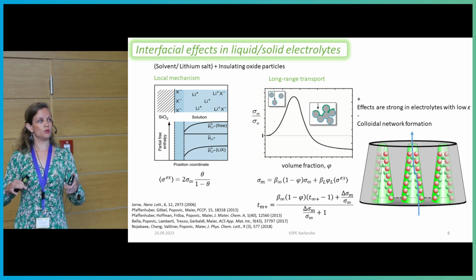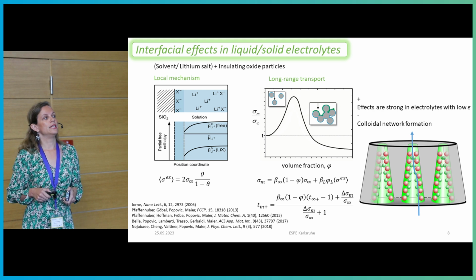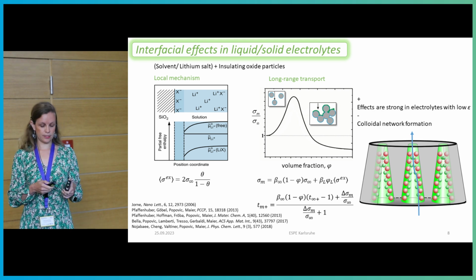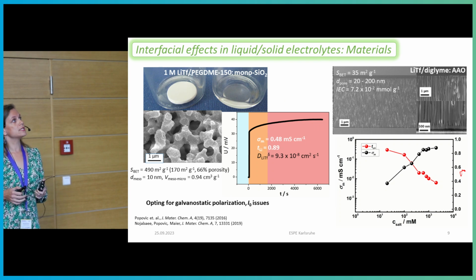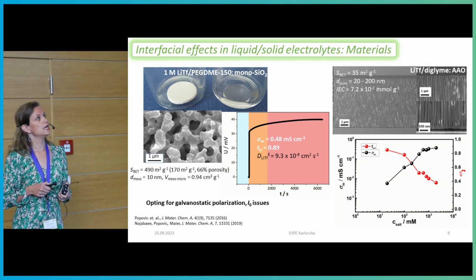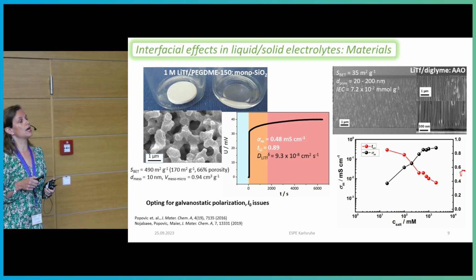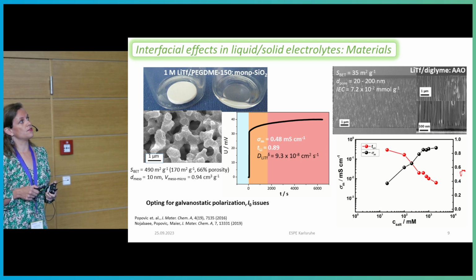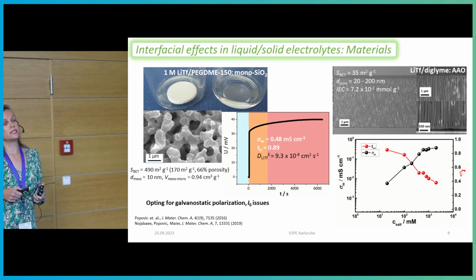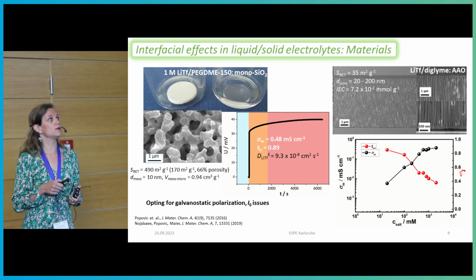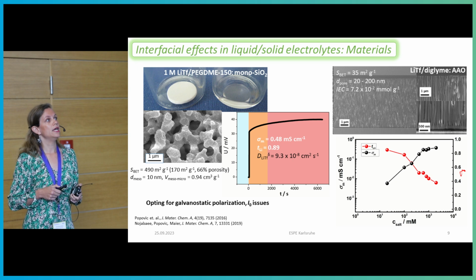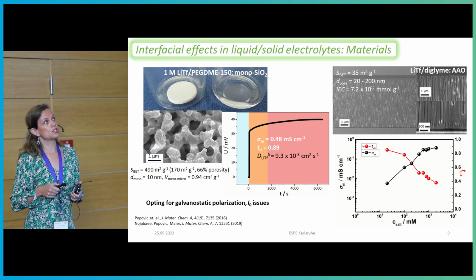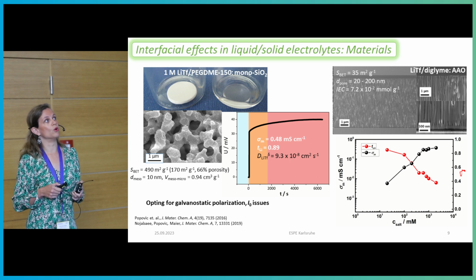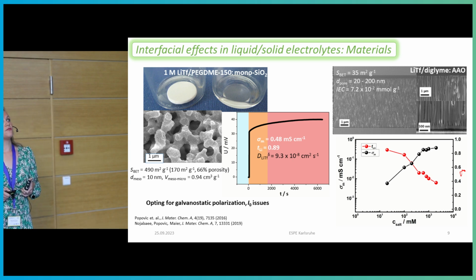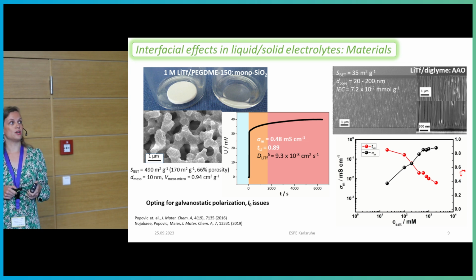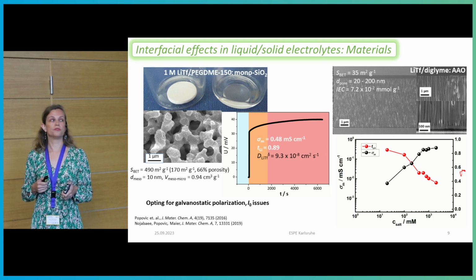So this is the reason why we try to invert the situation and make a material that is actually porous and infiltrated with a liquid electrolyte. So I'm showing you two of these examples. So one is a hierarchically porous silica that is infiltrated also with a glyme type of electrolyte. And here the surface area is very high, the porosity is also very high, thus the surface effect is very high, and then we end up with transference numbers that are very, very high. In terms of another material, which is anodic alumina, where we have a relatively low surface area, we can achieve high transference numbers at very low salt concentrations, because then we still have the chance to absorb all of the anions.